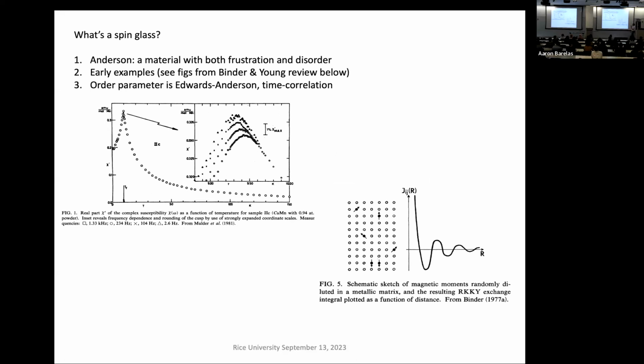Anderson basically expressed the fundamental materials requirements, which are a material that has both frustration and disorder. And so some of the first spin glasses were copper. If you put 1% or even 0.1% of manganese in copper, it'll show this behavior. It's really amazing because, I mentioned percolation physics. If the interaction between manganese were short range, that would be well below the percolation threshold. You would not see that. You would just see a rise all the way down to T equals 0.